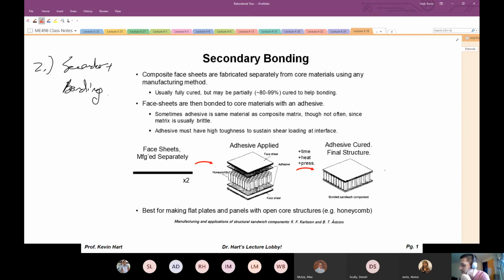All right. So these face sheets are usually fully cured, but maybe partially cured. Why would we want to partially cure them? Well, if you have some residual moieties, some residual chemical species left over in your face sheets, then you're going to have a better bonding with this adhesive and ultimately with the core that you have. All right. So how do we get to 80% cure? Well, good thing we talked about cure kinetics and you know how to do that. So remember when we talked about cure kinetics, we talked about these secondary or advanced manufacturing techniques with secondary bonding, co-curing, all those sorts of things. So this is one place where you might want to do that to increase the bonding between the face sheets and the honeycomb structure. All right.